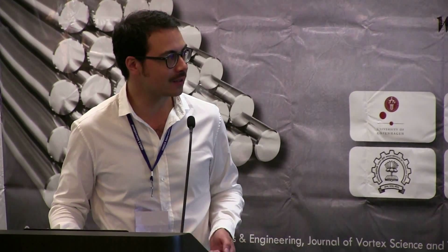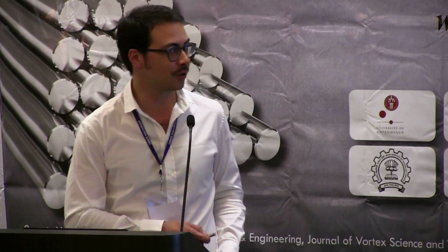as a first result. So we just saw SMA training with the same parameters applied on wires made with different parameters, and the SMA wires were tested and their SMA characteristics determined. Despite the same training parameters, the SMA characteristics are strongly deviating, and so our conclusion is that variations of the production process parameters cannot be compensated by a subsequent SMA training.